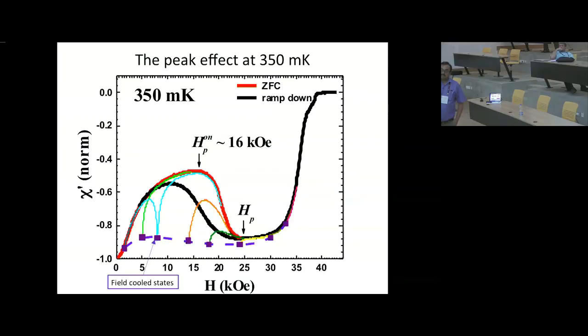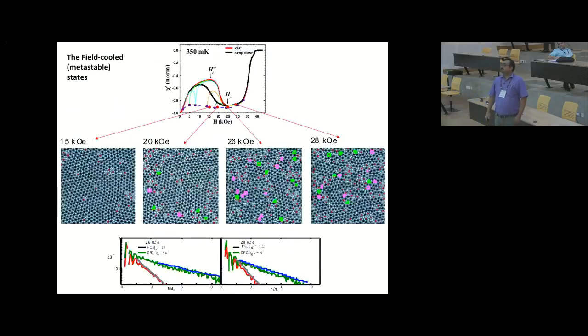Now these are the field cooled states, and in principle this is what I showed you for the 15 kOe state before, that these have to be highly disordered metastable states. You can see from susceptibility that they are metastable states, because if you start from here and try to increase the field up or down, it doesn't follow this line, but it quickly goes and merges with the equilibrium line. Now these field cooled states, this image is here. So these field cooled states are defective states.